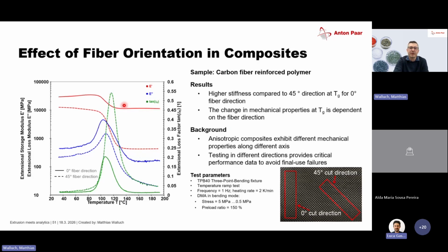Just another example for DMA, how it can help us. For example, if we have a fiber reinforced material, we can see, of course, the thermal properties don't change if we change the direction of the cutting of our sample. So this means we have higher reinforcement in one direction than in the other, which just leads to a change of the modulus. But the glass transition temperatures and so on, of course, is not touched by that. But we can see the mechanical properties change significantly.